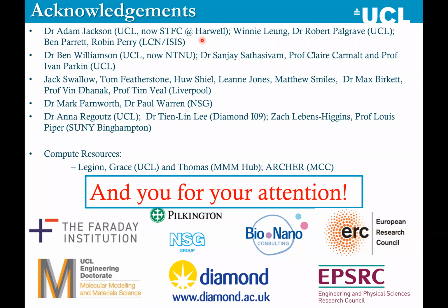So the meta-analysis was all experimental. Basically on the experimental, because when we had originally started this molybdenum doped indium oxide work, we found 30 papers, and 27 of those papers had found that IMO was better than ITO, but they were being published in journals that people wouldn't even see these papers in, right? And because I think reviewers and people in the field were so scared of a new idea, and because it didn't have an explanation, they just didn't believe it. So they assumed it was wrong. That's the only conclusion I can come to, that the field was just not ready for something that was saying that ITO wasn't as good a material.